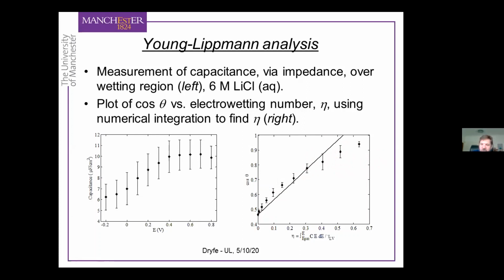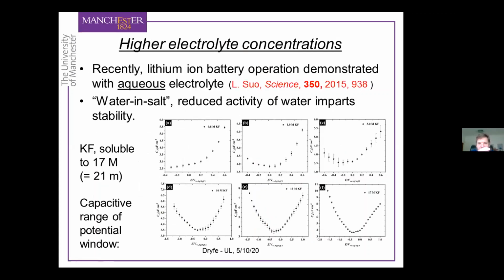And also, as I mentioned, because we think the capacitance of the graphite interface is sensitive to these specific ion effects, we really want to look at how this capacitive phenomenon changes as we change the identity and the concentration of the ion. So just to change subject slightly again, I've been talking for the last 10 minutes or so, these capacitance data was always done at quite high electrolyte concentrations, sort of 5 or 6 molar, so we could eliminate diffuse double layer effects from our calculations of capacitance.